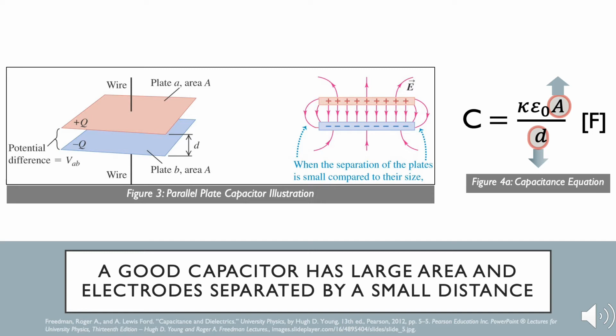In this composite, the two electrodes are in intimate contact, but with an energetic barrier for charges to pass from one to another, and so the composite can have an enormous interfacial area, separated by a short distance defined by the extent of electronic orbitals of the materials. The enormous capacitance of this geometry can maintain a large power density while significantly increasing its energy density. Again, our goal is for this research on heterostructure composites' electrical properties to provide a foundation for exploring high energy and high power density capacitors.